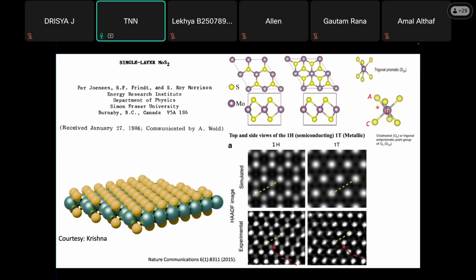You can also, with certain strain, rotate or slide the top sulfur layer, and it can form an octahedral or trigonal antiprismatic symmetry, the point group Oh, also with a D3d symmetry. Now the interesting aspect is that just by sliding one sulfur layer over the other layer, you can undergo a phase transition from metallic to semiconducting to metallic. And this is a reversible phase transition from metallic to semiconducting to metallic and back.